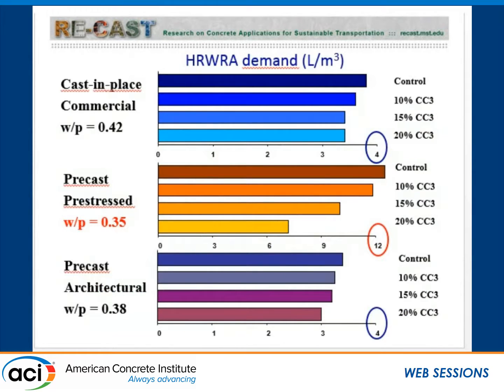So I'm going to compare the results. It's going to be always the 3 classes of the concretes. It's going to be bar charts. With the first one, it will be the control without any calcium carbonate, and then going 10%, 15%, 20% replacement by mass of the calcium carbonate with the 3 micron D50. So this is the superplasticizer demand to maintain, in this case, a slump flow of 640 or 650. You see the superplasticizer demand because of the better packing density and the reduction of the Portland cement.